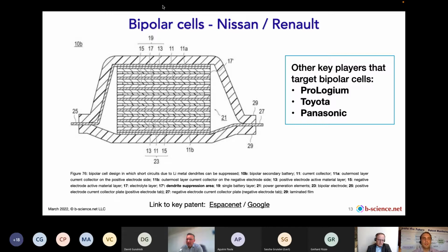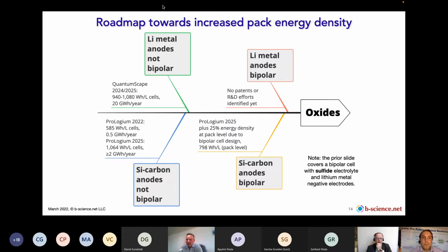But the production of these kinds of cells is very challenging, in particular avoiding formation of short circuits and the growth of lithium dendrites between these many layers, which all should work and not fail, as there is a serial connection. So it leads to what I would characterize as a roadmap towards increased pack energy density in terms of the technical decisions that have been made in this context, that are twofold in terms of the key decisions: whether to focus on lithium metal anodes or silicon carbon containing anodes, and whether or not to target bipolar architectures or conventional ones.